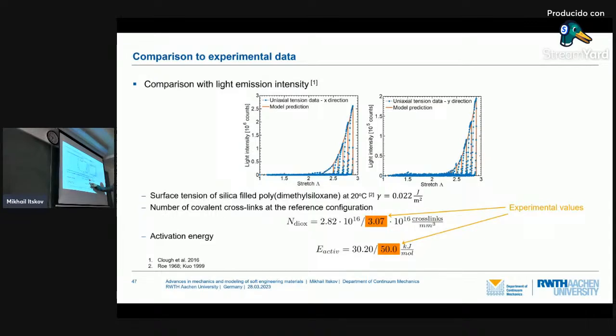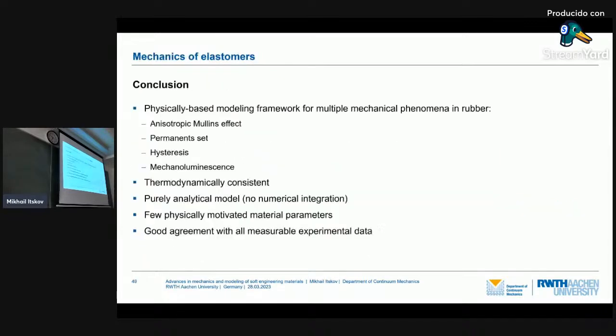The only deviation we still have is with the activation energies. Right. Let me summarize this part of my talk. We have presented a physically based model which is able, in one framework, to consider many different effects in rubber: anisotropic Mullins effect, permanent set, hysteresis, mechanoluminescence. And the model is thermodynamically consistent, and there is no need for numerical integration to take into account this anisotropy because of the analytical integration.